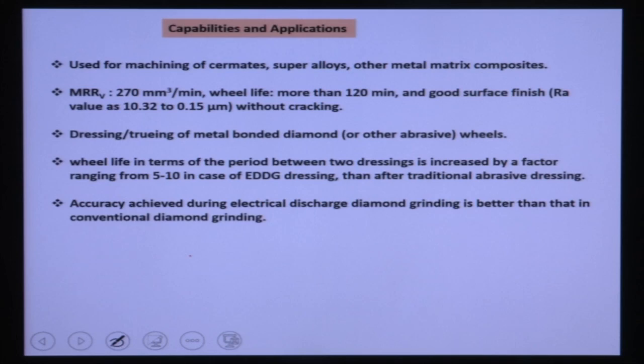Dressing and truing of metal bonded diamond wheels, or other than diamond, any kind of metal bonded abrasive wheels can be done. Any kind of contour shapes can be generated, and wheel life, in terms of the period between two dressings, is increased by a factor of 5 to 10 times in electro-discharge diamond grinding dressing compared to traditional abrasive dressing operation. The accuracy achieved during electrical discharge diamond grinding is better than that of conventional diamond grinding. So, thank you.